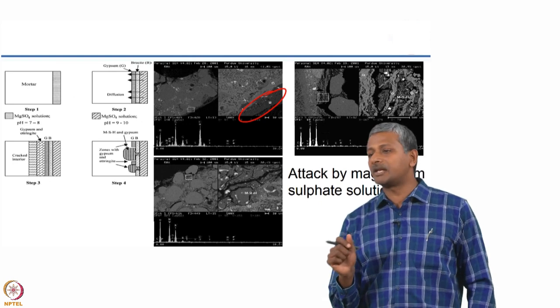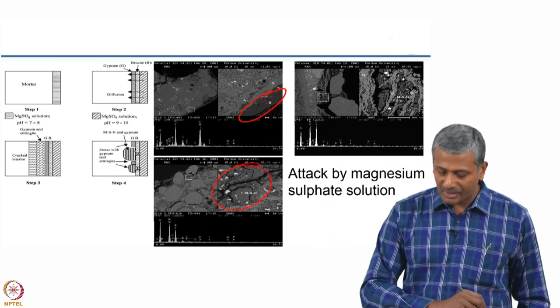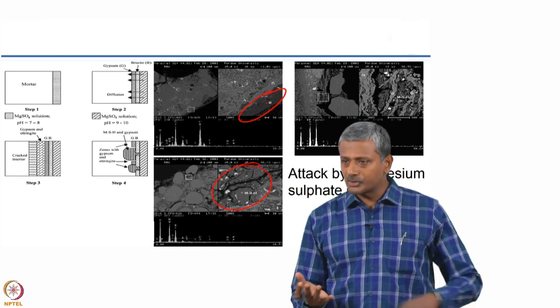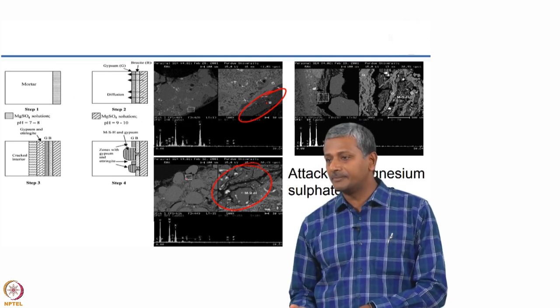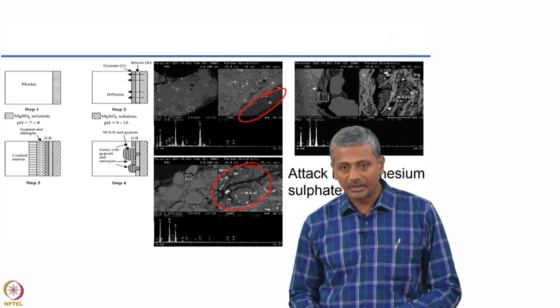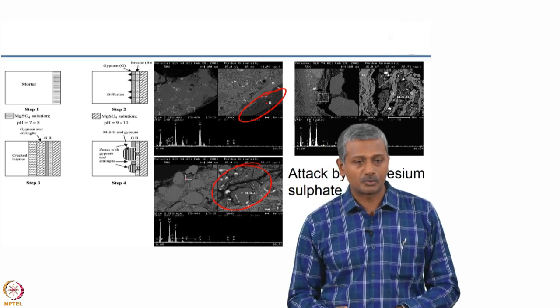In the case of magnesium sulphate, a brucite layer forms on the surface at very early stages of attack, acting like a protective skin that prevents further penetration of sulphate for some time. But due to its propensity to keep removing calcium hydroxide, it ultimately leads to CSH being completely transformed into magnesium silicate hydrate, which has no significant binding characteristics. The attack therefore depends a lot on the cationic species involved. In most cases — calcium, iron, sodium — the sulphate itself is the primary attacking agent, but for magnesium, the cationic role is also very important. With ammonium sulphate, because of extremely high solubility, an even more dangerous attack can occur.